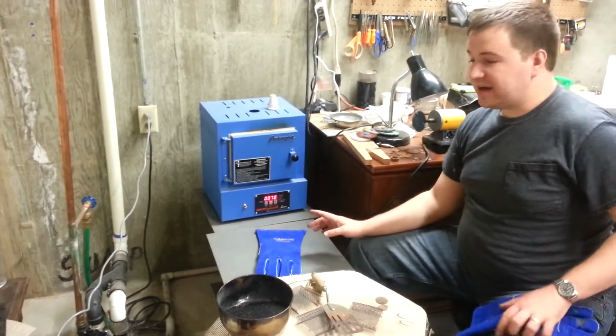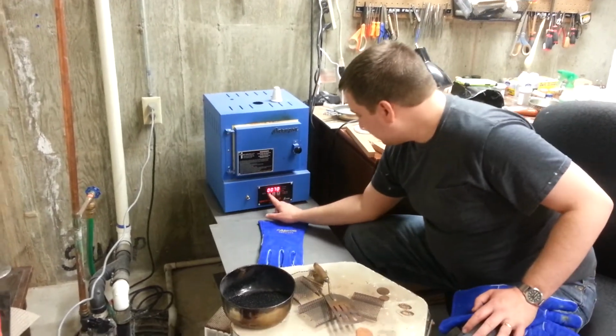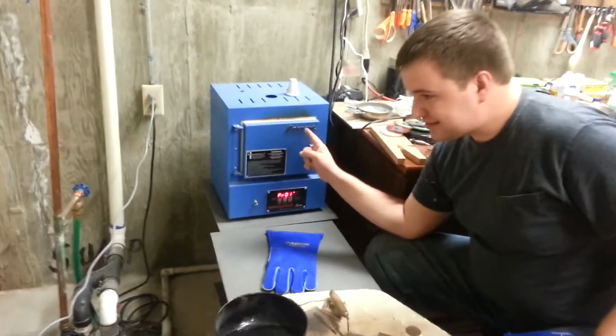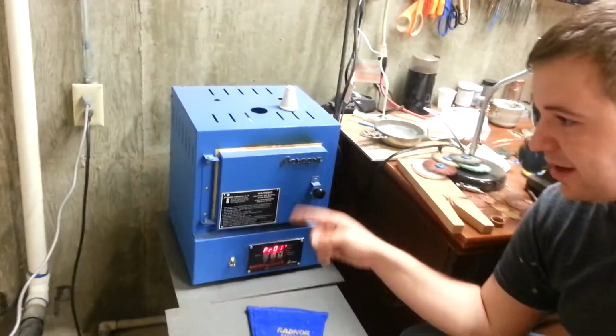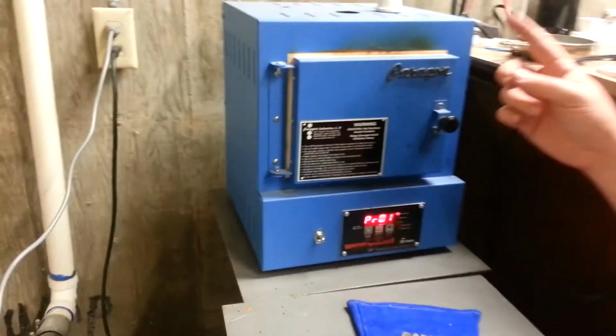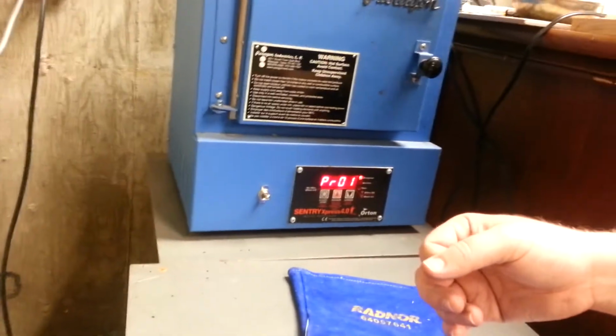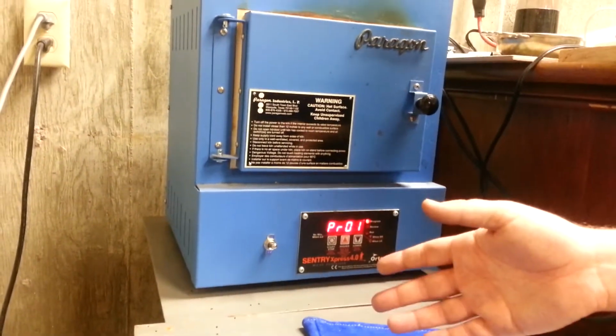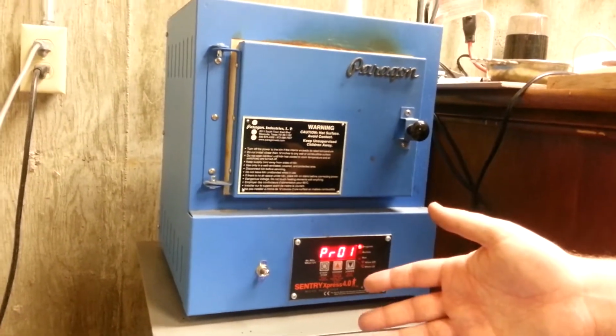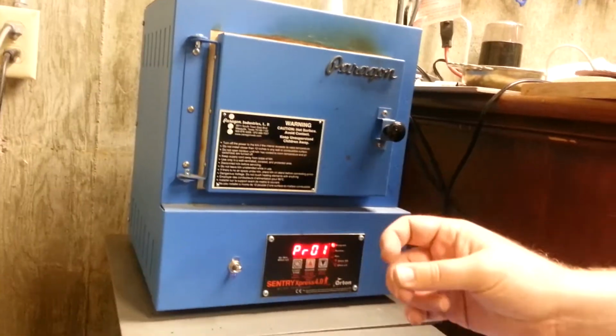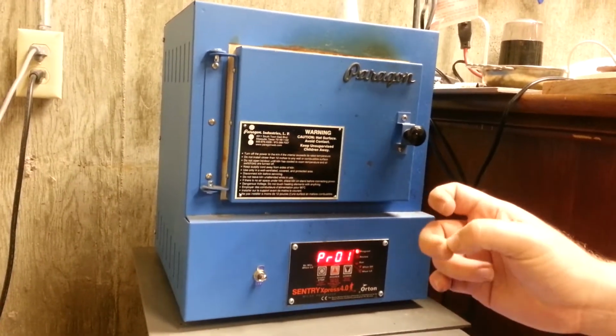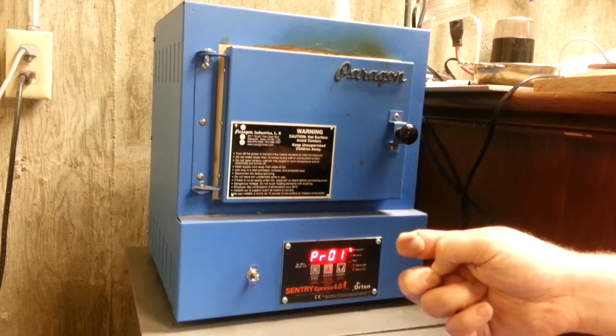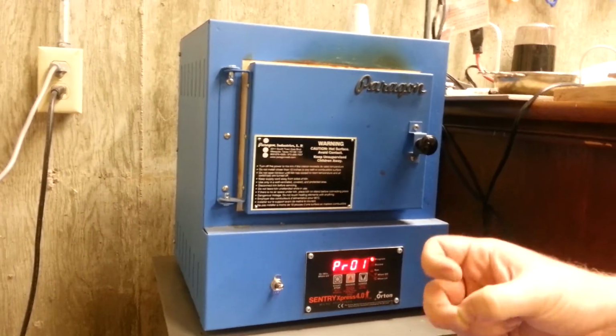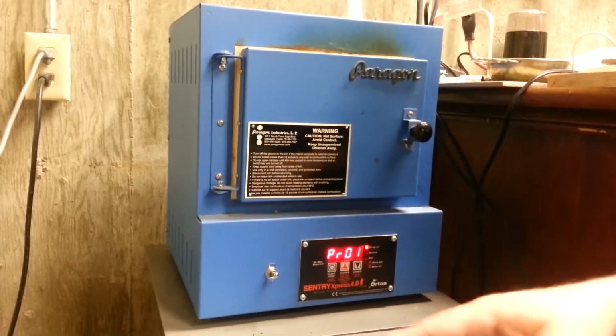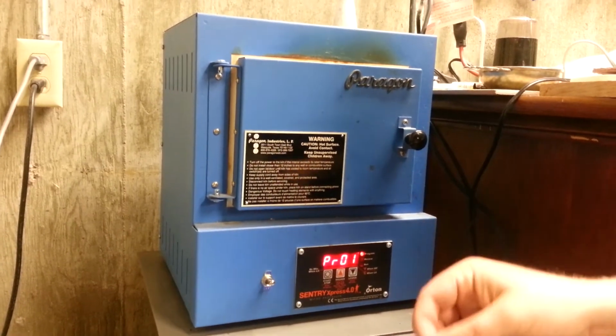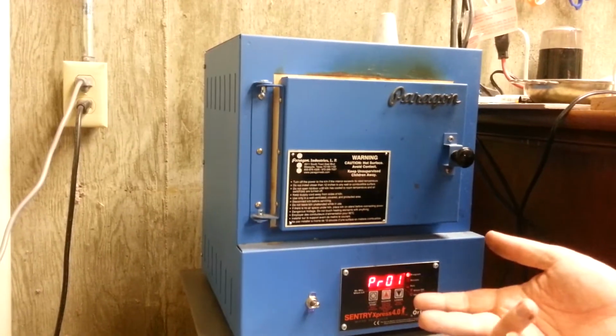For the second phase of firing, it takes a little bit longer. And I'm going to pretend that this is bronze. This is actually copper. You can fire copper like bronze, but you can't fire bronze like copper. Copper can be fired up to about 1700 degrees for a couple hours, 2.5 hours at full ramp. Bronze is more like 1545 degrees Fahrenheit. If you go too high, you'll get bubbles in your bronze. It'll be totally destroyed. If you go too low, the bronze won't sinter at all.